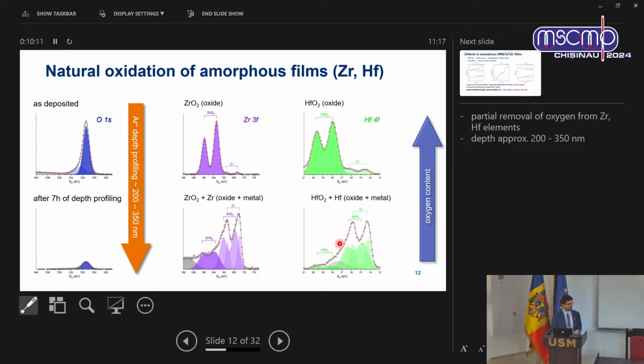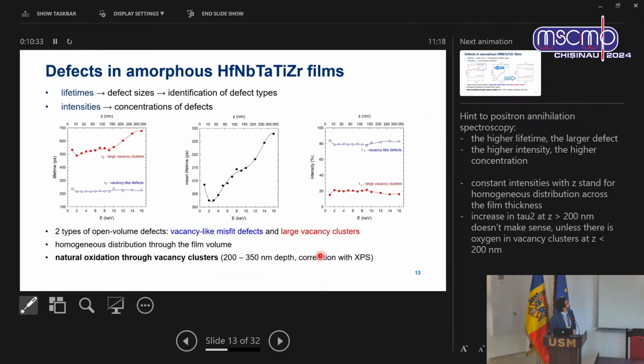And to answer the question why it happened so deeply in the case of these films, it was not just the chemistry, that the composition means that it has to oxidize, but we needed to know the process, the mechanism of the oxidation, and for that we found it quite useful to use the positron lifetime spectroscopy. Quick repeat: if you look at the lifetimes, you observe basically the defect sizes and identify the defects. If you look at intensities, it correlates with their concentration.